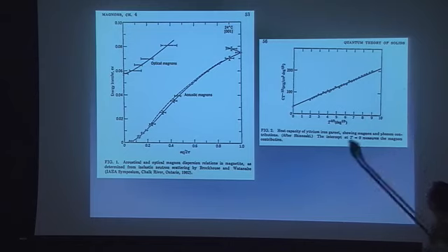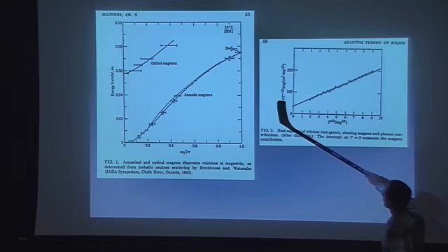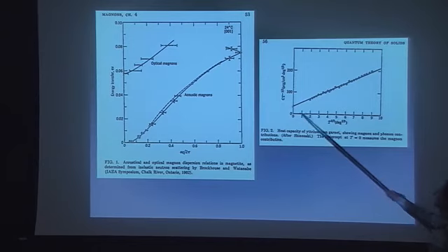phonons and magnons. And again, the way to disentangle the two is to plot the measured heat capacity as a function of T^(3/2). And the quantity that is plotted is specific heat divided by T^(3/2). And in this representation, the straight line here will give you the phonon contribution, and the intercept here at T equals 0 gives you the magnon contribution, showing again that this T^(3/2) that we found is experimentally observable. And there are other experiments that you can find in the literature which show this type of thing. Okay, so this is some magnon data.